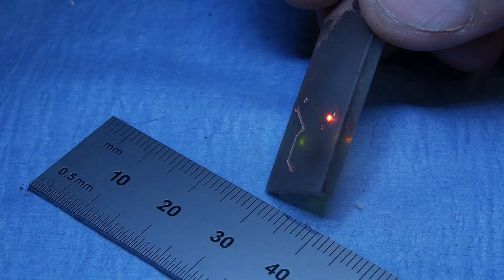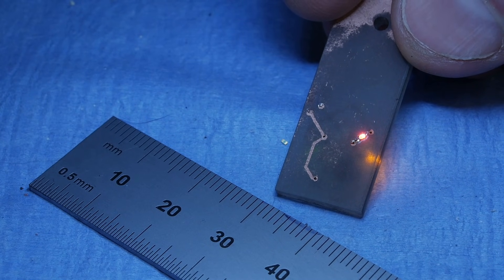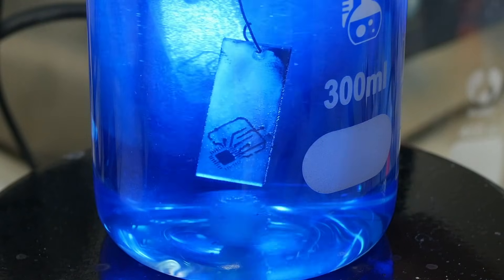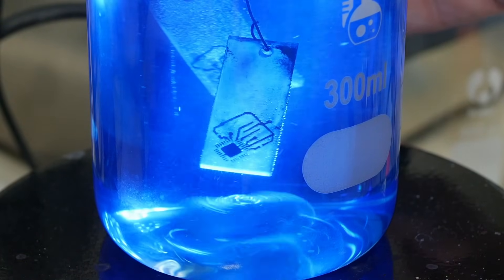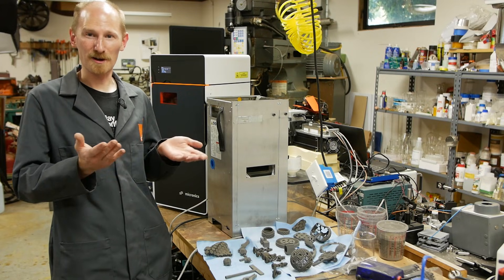At the end of the video, the biggest problem I had is that the copper traces didn't have good adhesion. They would basically just peel right off the surface. And the reason for that is that the catalyst I was using that created the copper was just applied to the surface. There really wasn't any good adhesion there, and the traces would just peel off. It was not usable.